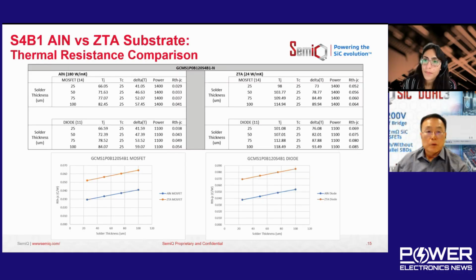Yes, we offer the aluminum nitride version too. I was going to ask about that. You've got some with aluminum nitride and some with the pre-applied thermal interface material. How does that improve the thermal performance of the module versus the other products in the portfolio? So in the beginning, we started with zirconia-doped alumina substrate, and you can see this is the thermal simulation result of aluminum nitride. It has a much better thermal conductivity, 180 watts per meter Kelvin versus zirconia-doped alumina at 24 watts per meter Kelvin.